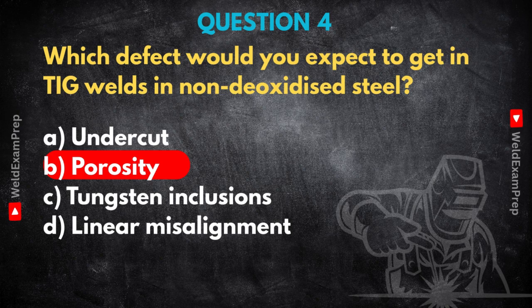So gas is being created right there in the molten pool. Exactly. And if that gas bubble doesn't manage to escape before the weld freezes, which happens quite quickly with TIG, it gets trapped, resulting in porosity. Even with perfect external shielding? Even with perfect external shielding, it's a material issue. While you can get tungsten inclusions from bad technique in TIG or undercut, the porosity risk is inherent when welding non-deoxidized steel with this process due to its chemistry.